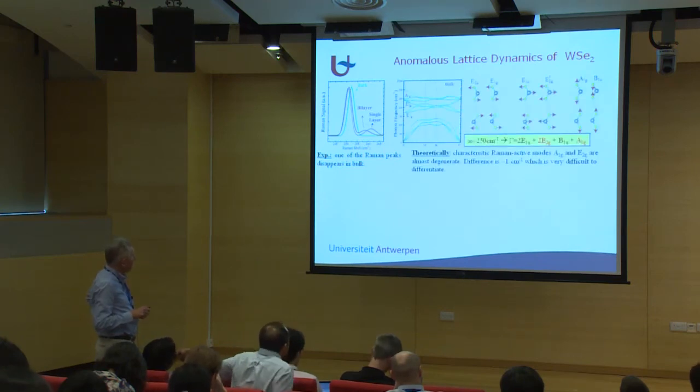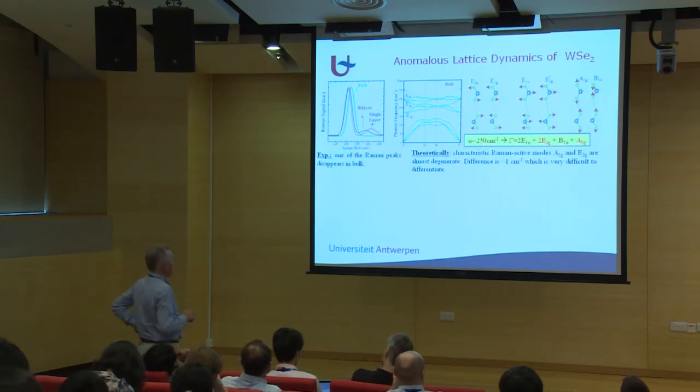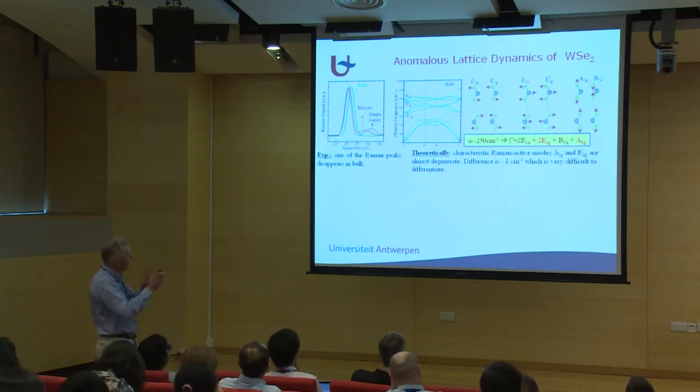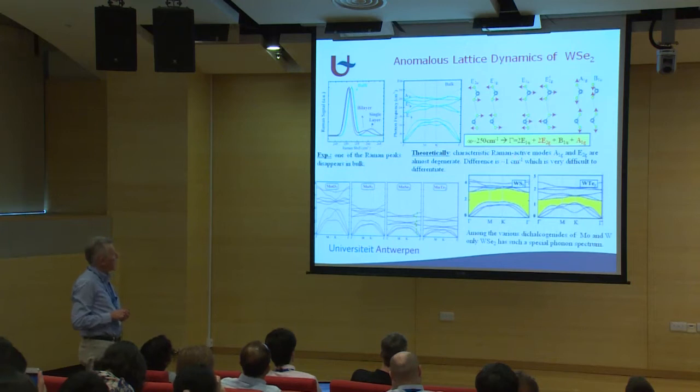Now, at this point, and that's the region we are looking at here, around 250 cm^-1, the phonons which are present there, you have the two E phonons. So that's this type of movement of the different atoms. The red ones are Raman active, and this one here is also Raman active. This is the out-of-plane mode. They all have the same energy up to 1 cm^-1.